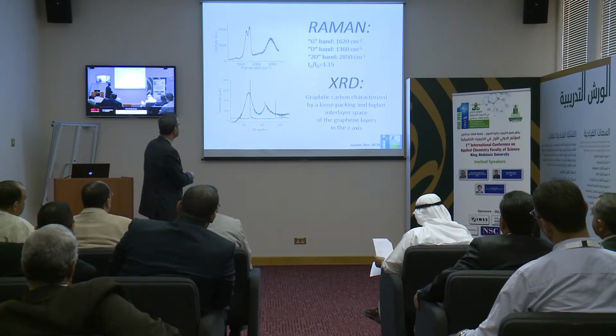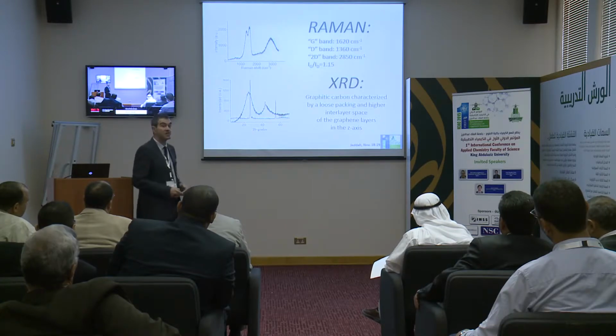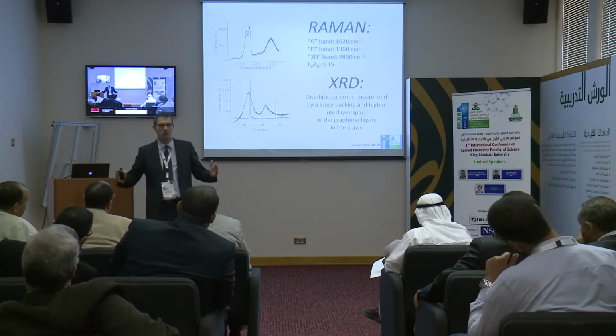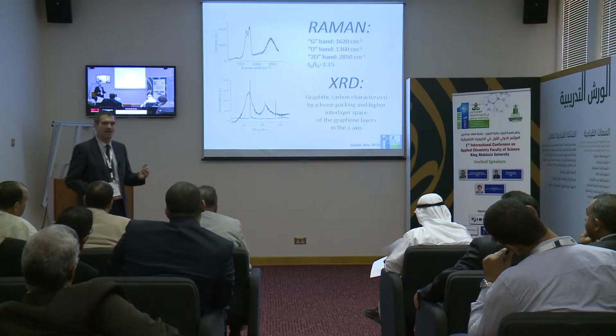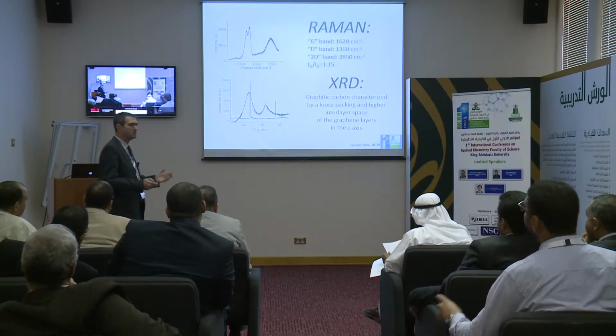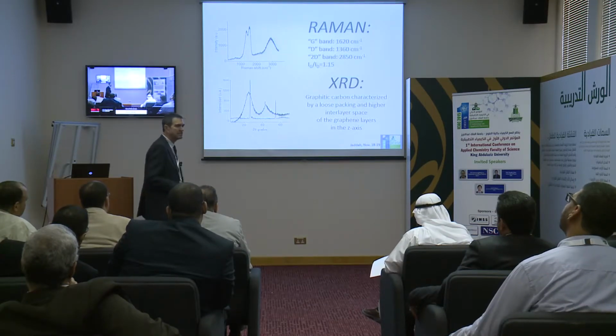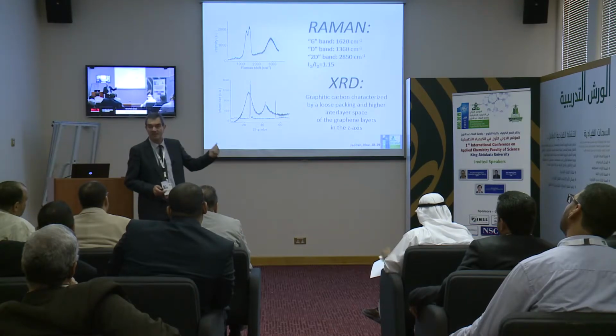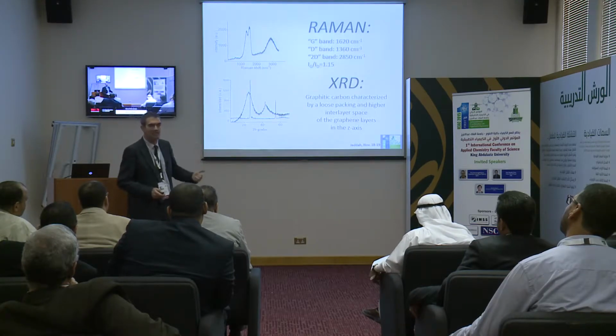However, the XRD of our material, of our carbon, is very similar to the graphite, except that the bands are very broad. So this means that the crystallization of our carbon is very poor, so we have something that is very poorly crystallized, and for this reason we call it graphitic. So it's not really a graphite, it's graphitic.